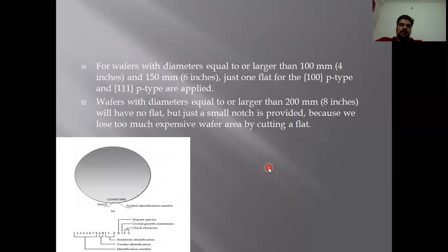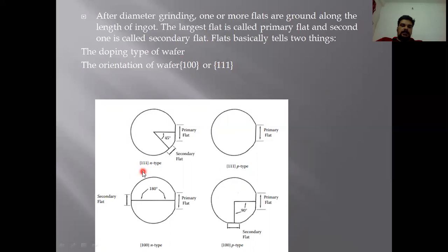As you can see, for a 111 N type silicon wafer, this is the primary flat and this is the secondary flat, and the angle between the primary and secondary flat should be 45 degrees. So by seeing this type of wafer, we can tell that this is an N type silicon with orientation 111. Now for 111 P type, there is only a primary flat here. But if the angle between primary and secondary flat is 180 degrees, then it is a 100 orientation type.